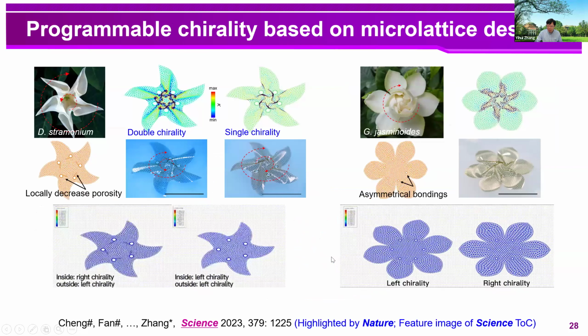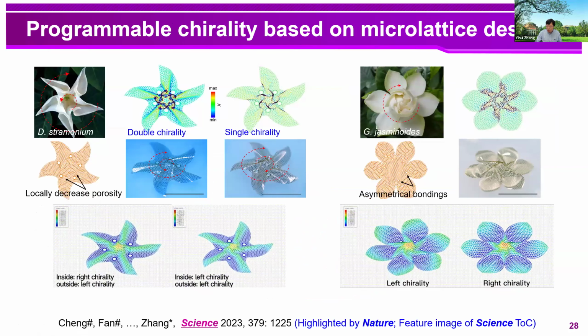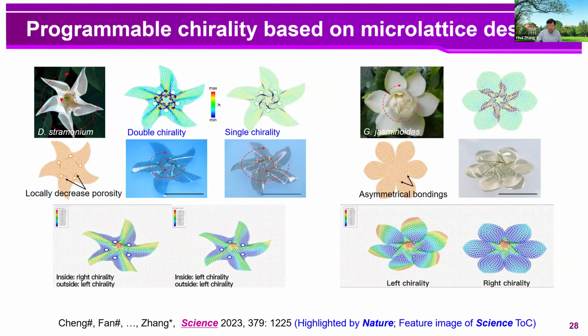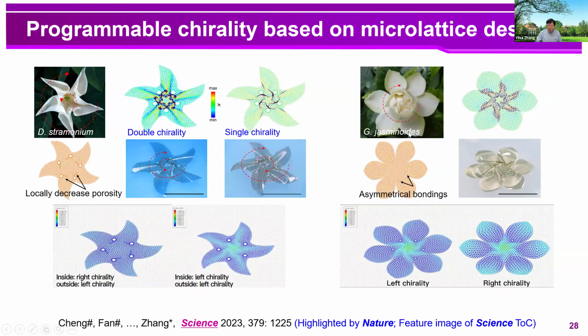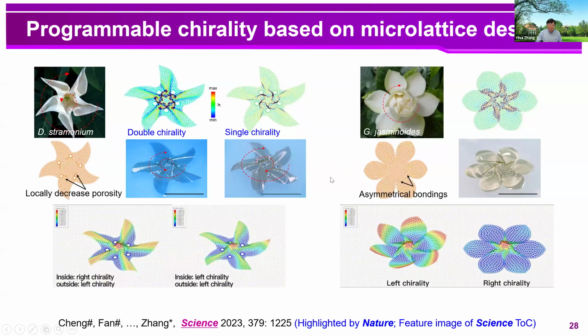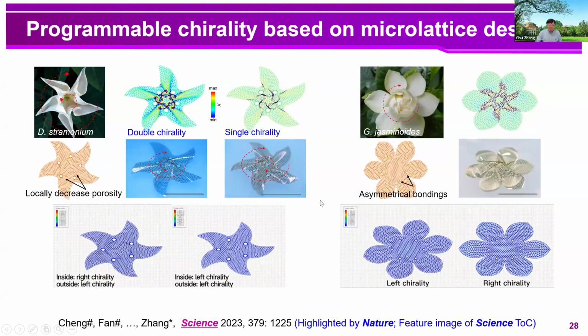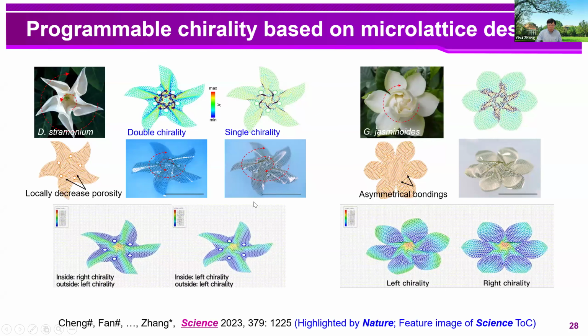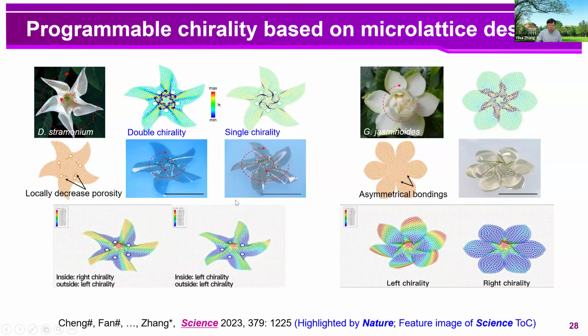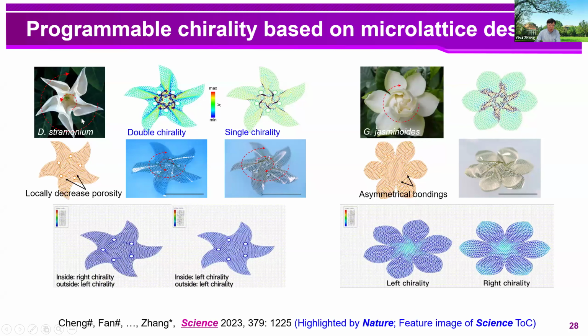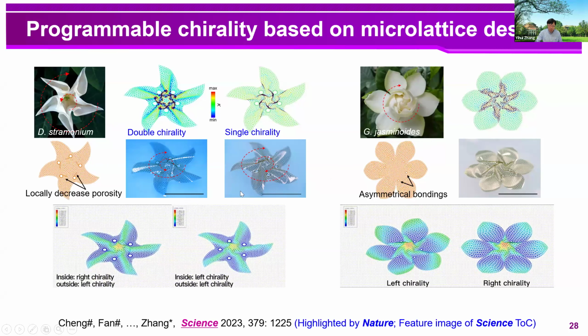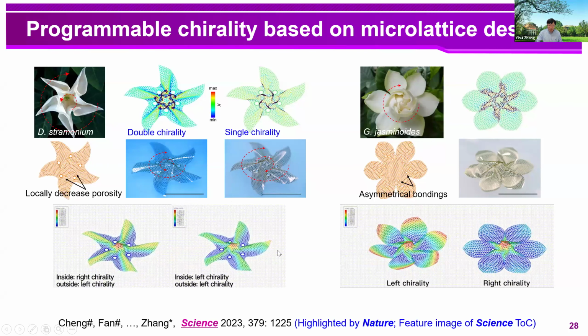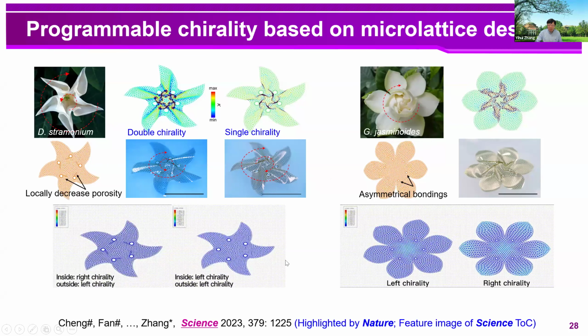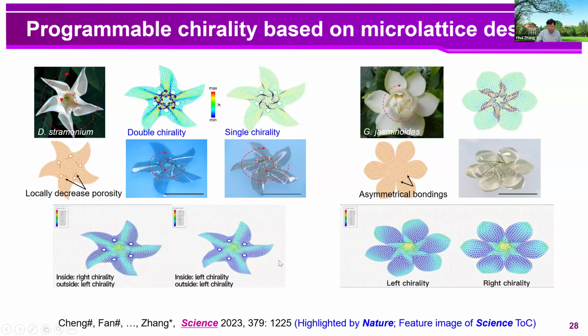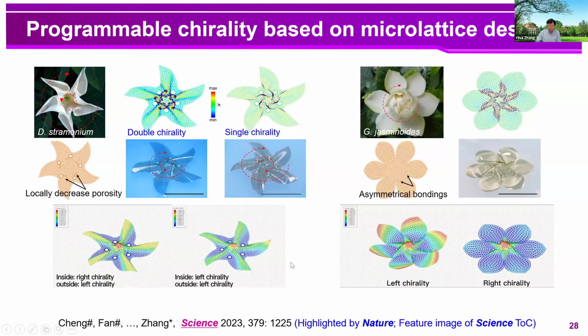And then we first show the capabilities of this microlattice design by using two flower surfaces as our design targets, including this stramonium and the jasminoid flower. And both of these surfaces have a certain degree of chirality. And here, by using our microlattice design, we can leverage the discreteness mediated deformation and introduce locally controlled porosity distribution to reproduce this chirality in biological surfaces. And here, by modifying the local porosity distribution, we can even change the chirality of the assembled 3D surface.